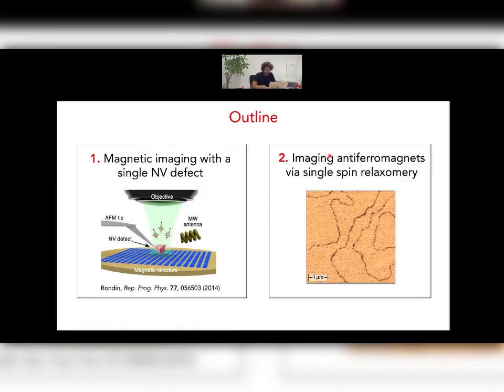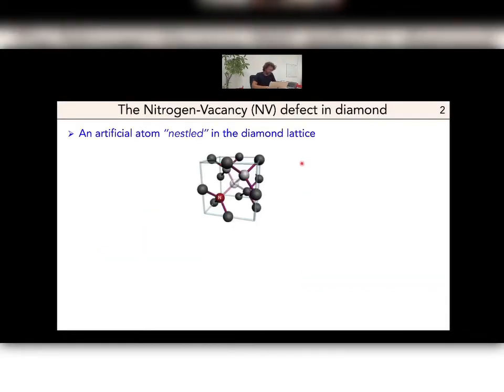antiferromagnetic material. So I start with the NV defect, and the NV defect is a point defect in diamond that corresponds to the association of a nitrogen atom, a nitrogen impurity, that is associated with a missing carbon atom, a vacancy in a neighboring lattice site. And this complex will lead to the formation of discrete energy levels within the band gap of diamond.